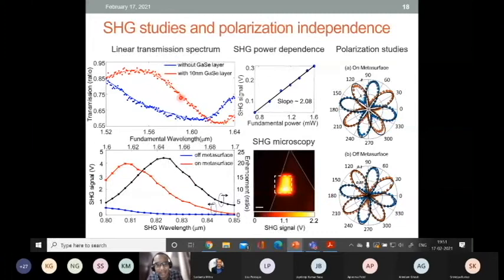And then when we characterized these structures, we soon realized that because of the underlying lattice arrangement being hexagonal, true polarization independence can be achieved only for the zeroth order diffracted SHG signal. So one has to restrict the collection angles in a way that you selectively collect only the zeroth order diffracted signals. And this is some polarization results we have obtained where we look at on grating and off grating, so on metasurface and off metasurface.